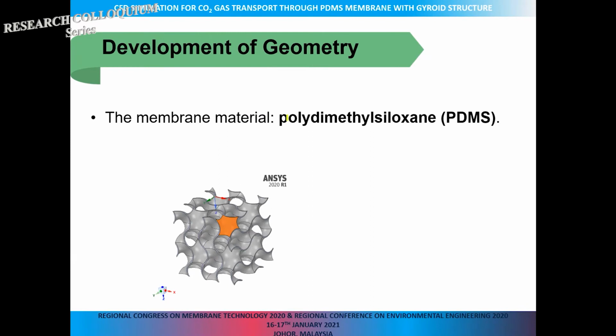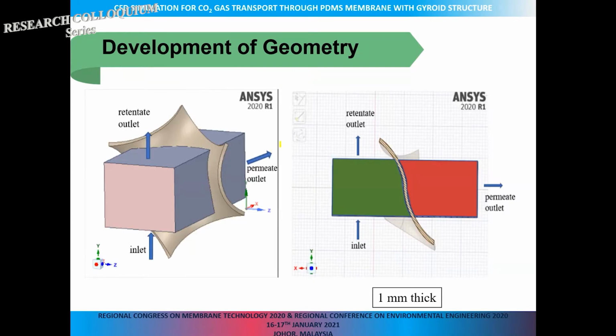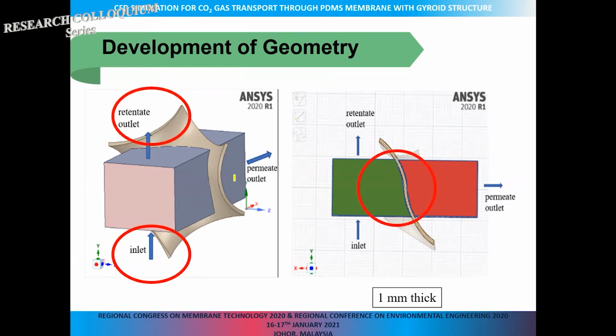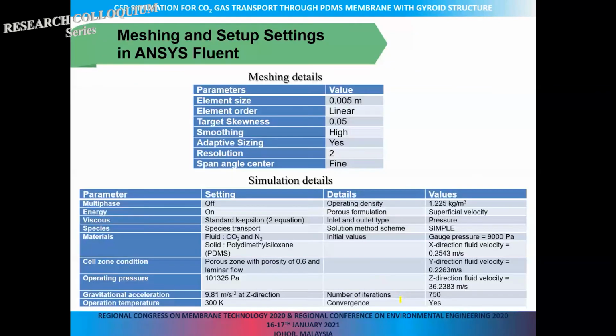For the development of the geometry, we use MATLAB to generate the code and then use the code to draw the gyroid structure of the membrane. You can see that when we run the simulation, we only take one unit size of the membrane. The material that we use is PDMS. We have the inlet and outlet and also the permeate. This is the membrane thickness, and we set it at 1 mm because this is the thickness value we can get from the literature for the CO2 permeability of PDMS with the structure. And then these are the settings for Fluent. The simulation was conducted until it reached convergence.